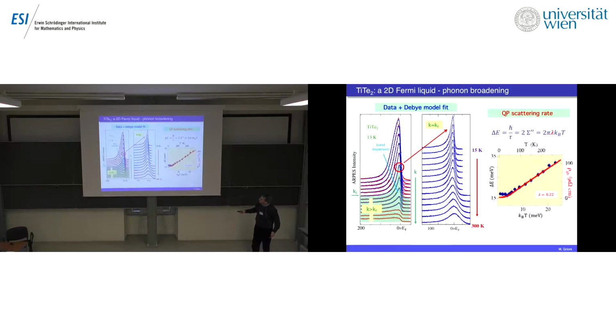displaced oscillator. Now, in a solid, things are never so clear because you have many vibrations of different energies, and you do not excite, in general, just one particular vibrational state. So what you may observe is something like this. These are spectra of a two-dimensional Fermi liquid system, titanium ditelluride, and what you're supposed to see here is the dispersion of a peak, which represents a metallic band that goes to the Fermi energy. Then interesting things happen actually also beyond the Fermi energy, but I will not tell you about this today.